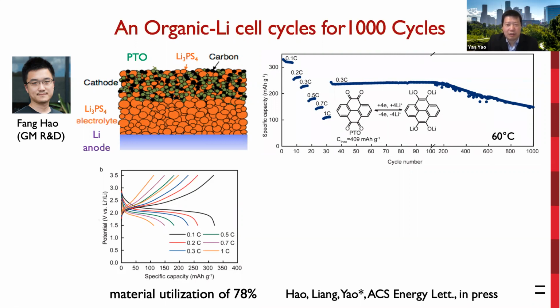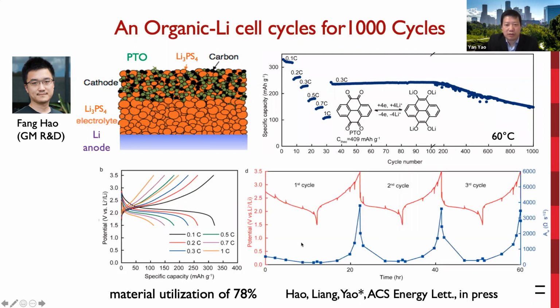To understand the stability, the evolution of the cathode electrolyte interface was probed by in situ electrochemical impedance. The Warburg coefficient can be extracted from the electrochemical impedance spectra, which reflects ion diffusion resistance at the cathode electrolyte interface. What we see here is that the AW remains low during the majority of the cycle, but increases sharply when the voltage exceeds 2.9 volts versus the lithium, at which the potential oxidation of electrolyte is expected.